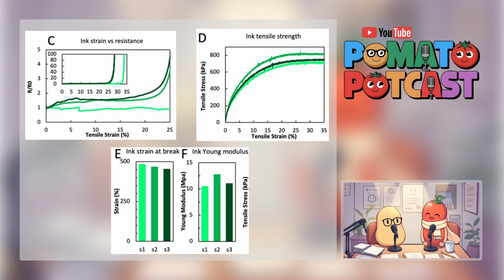Electrically, you can stretch it by, say, 22 to 30% before the resistance starts to climb significantly. Okay, so quite a bit of give. Yeah. Electrical failure, where it stops conducting reliably, happens around 28 to 33.5% strain. But does it snap then? Oh, no. Physically, the material itself is way stretchier. It doesn't actually break until you stretch it like 450 to 485%.